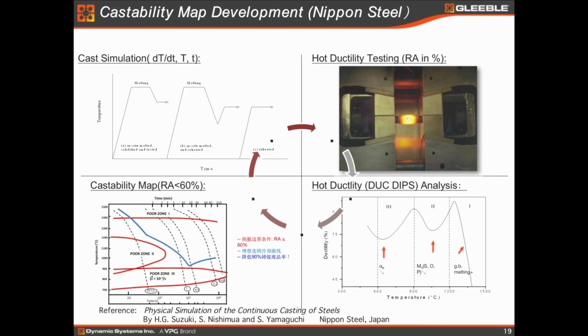And the biggest challenge he told me is that we are talking about peritectic steel. Because in that type of steel, the carbon content is normally from 0.09% to 0.12%. The shrinkage from liquid to solid is huge, or let's say the maximum. And if you don't control it well, the gap between the shell and the mold is so big that you would generate lots of uneven shell thickness. And as long as you have uneven shell thickness, you would have a problem.